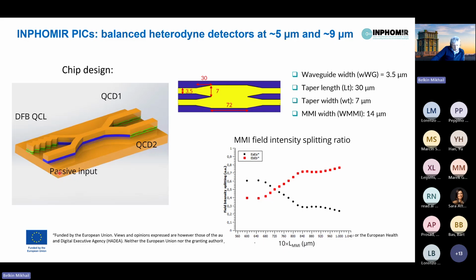It is based on 2 active regions. One is the active region for the quantum cascade laser, and a separately grown active region for the quantum cascade detectors. And then we have a 2x2 MMI, where it is designed to have a 50% splitting of power for the 2 inputs.